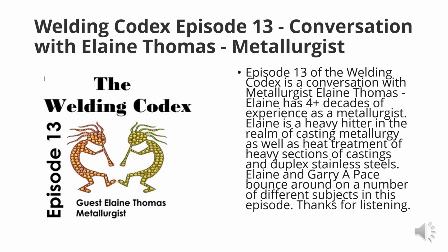What are some of the difficulties that you ran into in the early years trying to cast this stuff? Okay, I've split some of those big ones right in half, and it's not pretty. Because there's so much nitrogen in this alloy, you have to be very careful to limit the amount of nitride formers in it, such as aluminum. Since the AOD uses aluminum as a fuel to actually heat up the molten metal, again, there's a lot of thermodynamics involved there. You can end up with a trace amount of aluminum that might not be so trace, and you can end up with aluminum nitrides, and that baby can just rip that part in two. It's like making a piece of Chihuly art glass that didn't get tempered. It just shatters, okay? Not good.